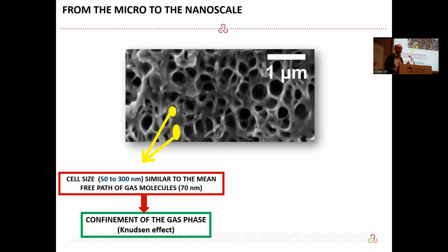So one of our topics in CellMat, in our group, has been producing these materials, finding ways to produce large samples of nanocellular polymers, testing the properties, and trying to investigate whether the properties are better or not. From the microstructure point of view, a cellular polymer with cells in the nanoscale has two interesting expected behaviors, at least theoretically. On the one hand, the gas phase, the gas inside the cells, could be confined, for instance. The cell size could be, for instance, between 50 and 300 nanometers, although later I will show some materials with lower cell sizes than this. And these values are around the mean free path of air at atmospheric pressure and room temperature. So we are in similar values.